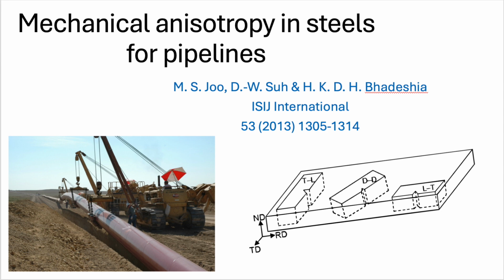Right. Measuring that toughness usually comes down to the Charpy impact test. It's a standard. Right, the Charpy test. That gives you that S-shaped curve, doesn't it? It does. You hit a notched sample with a pendulum, measure the energy it absorbs at different temperatures. That curve shows you everything. So the top part of the S, the upper shelf, that's where it behaves ductilely, absorbs a lot of energy before failing. Correct. That's the ideal tough behavior. Then there's the bottom part, the lower shelf, where it's brittle, snaps easily with little energy, that's cleavage failure. And the bit in the middle is the transition zone.